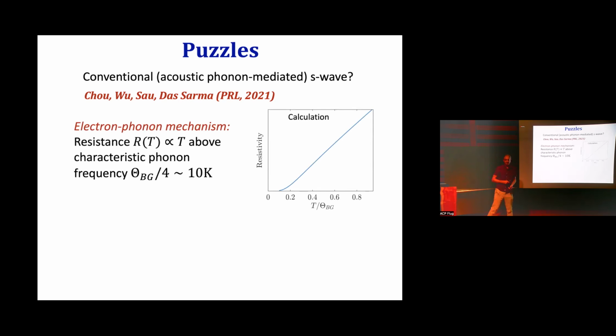Now, I'd like to tell you why I think this might not be applicable here. Luckily, the mechanism of phonon-mediated superconductivity is so well understood that we can try to disprove it. If it is electron-phonon-mediated superconductivity, we should be able to calculate a lot of things and compare them to the experiment. In particular, the same electron-phonon coupling that leads to superconductivity should also scatter the electrons very strongly at elevated temperature. If it's strong enough to lead to superconductivity, the scattering of electrons in the metallic state should also be strong. And we know that that should lead to an electrical resistance in the normal state that goes linearly with temperature above a certain characteristic temperature of the phonons, which we can estimate in the system should be around 10 Kelvin.